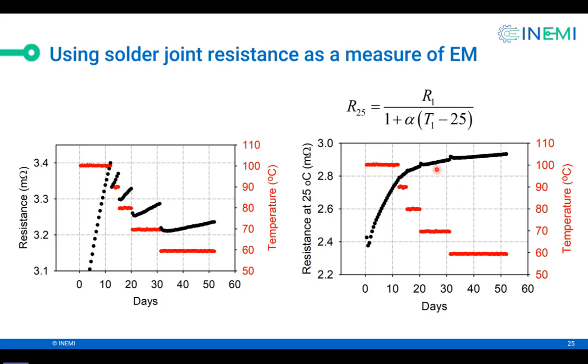Now, in this curve, the big unknown is alpha. So alpha is the temperature coefficient of resistivity. And this is a very unpredictable term. This depends on lots of stuff. It depends on the defects, point defects, dislocations, grain structure. So what value of alpha do we pick? So what we do is we play with this curve, and we keep changing the value of alpha until we get a good fit. So when the curves on the left converge into a smooth curve as shown here, we say, okay, that's the value of alpha. And typically it's about 0.0035 per degree centigrade in that range.